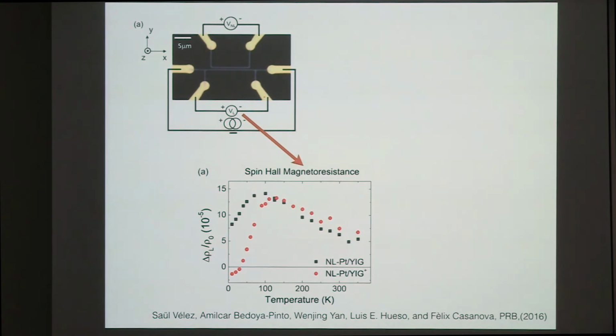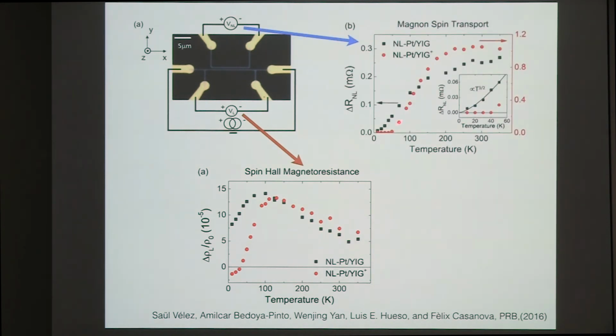And also, I think our experiment also relates to Felix's experiment shown yesterday. So yesterday he already pointed out this 90-degree coupling can explain the sign change here. But I want to further point out that it also will explain another factor in his paper. So this is the local measurement of SMR, but this is non-local measurement. Non-local measurement requires that you have injection of the spin in one of your channels and it travels in the insulator to be picked up in another channel. But if you look at this ion-milled device, this value goes to 0 at low temperature. That is exactly because the spin current is blocked by the antiferromagnet amorphous YIG at that time. So it's very consistent.